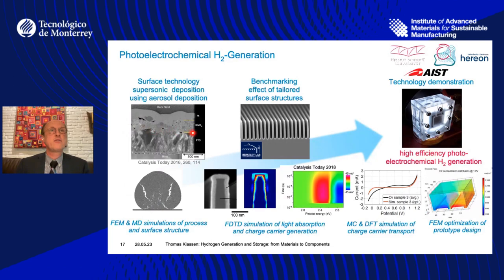The coating is only in this area, in this case, bismuth vanadate, which is a very good photoabsorber and has the right band gap. And this is on a substrate of FTO. That's the lower part, and on glass. So we can either shine light from the top or shine light from the bottom to make the reaction. So if we come from the top, we do the water splitting here. And the electrons have to diffuse to the FTO layer and are transported to the other electrode. If we come from the bottom, then we generate and pick up the electrons right at the lower interface of the bismuth vanadate layer.